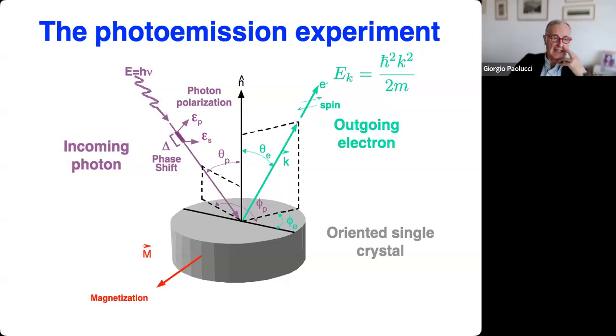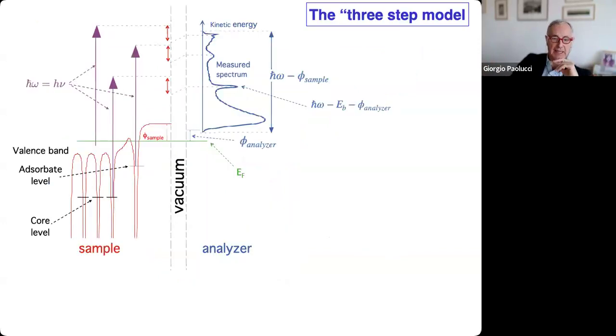So the basic idea is that you excite electrons from the sample, and because you know the characteristics of the incoming radiation, and you measure the angle of emission and the kinetic energy of the photoemitted electrons, you get information about the sample itself. This is a schematic in which you see on the left side the energy levels of the sample, and all the potential due to the atoms, which is modified when you move towards the surface of the sample.